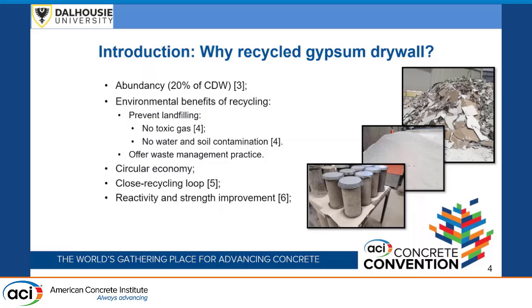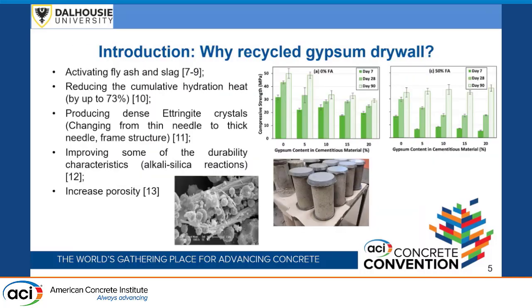So based on these, we are going to use recycled gypsum drywall and find what we have in the literature. In the literature, researchers typically use the fine recycled gypsum drywall to have a compatible particle size with the cement. They find that recycled gypsum drywall can activate fly ash and slag, and can reduce the cumulative hydration heat by up to 73%, which is significant for large projects.